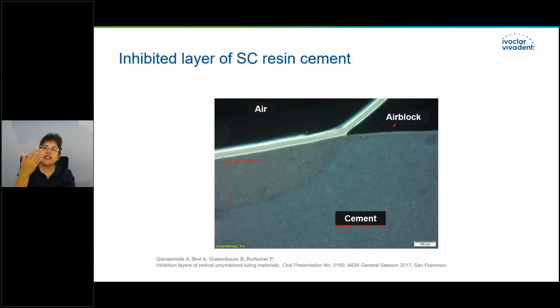After taking off the excess, there's a general recommendation to use an air blocking gel or glycerin gel on the margins. This is because of the use of resin-based cements, to avoid an oxygen inhibition layer. You can see here our air blocker is the Liquid Strip, and if you apply it, you will have a complete polymerization of the cement.